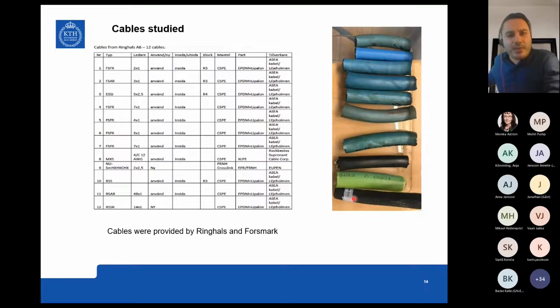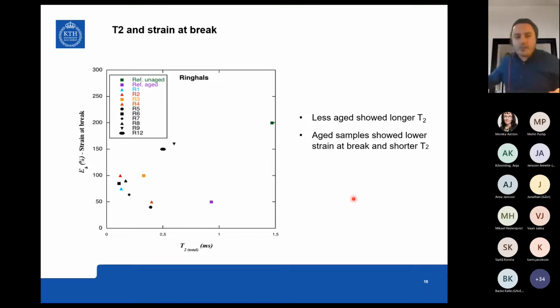So we had these cables from the nuclear power plants, and this is some of the data that we acquired. This is the transverse relaxation time, the T2. As I mentioned, a low T2, so this is 0 here, means that you have a very stiff material, so you don't have so much mobility in your material, compared to a high T2, which means higher mobility. And this is plotted against the strain at break. The two data points here: the green one, reference unaged, is a polymer which has not been aged and doesn't contain any steel or ferromagnetic components, so it's just pure rubber. And this other component is an EPDM, which has been aged at 170 for 100 hours. The reason I put these out is that I wanted to show that these are the cable data that we acquired, and these are the non-cable data.